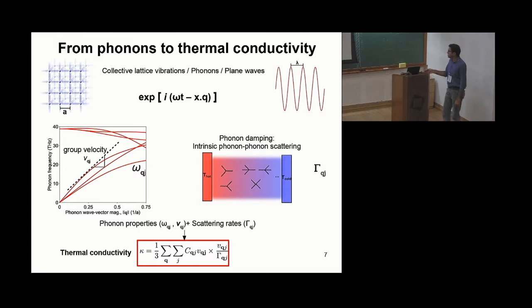The functions here are actually derived either from this curve or this curve. Heat capacity C is just a unique function of the phonon dispersion and temperature. V, as I said, is the group velocity of the phonons, again the same V, and gamma is the scattering rate. So when you have all these quantities for a given material, in principle, you can calculate the thermal conductivity of that material.